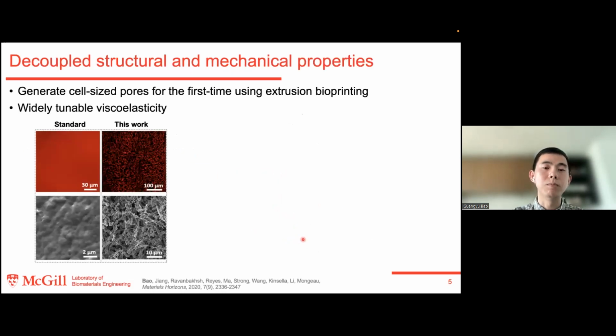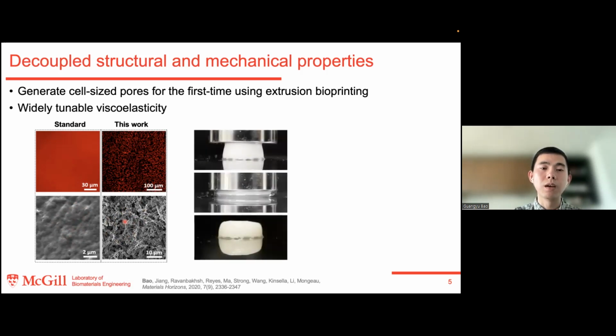After labeling the biopolymer with a fluorescent label, we can use confocal microscopy to visualize its internal structure. For the standard covalently cross-linked hydrogels, we cannot observe any pores because the pores are smaller than the resolution of the microscope. Similarly, from the SEM, we cannot observe any pores either. But the hydrogels made using our method form porous space. Similarly, in the SEM, you can also see the interconnected pores. And because they are highly